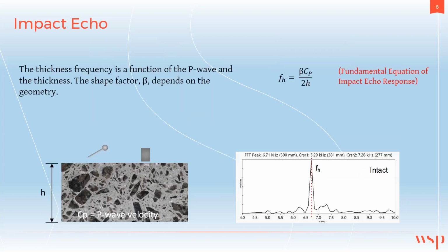The thickness frequency is a function of the compression wave and, of course, the thickness of the element that you're testing. Depending on the type of element, there's a shape factor that can be applied, but the fundamental equation for interpreting the thickness frequency is that shape factor times the compression wave velocity divided by the thickness of the element doubled, essentially because you have the time of travel to a reflected boundary and back.